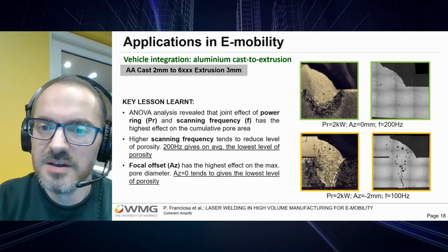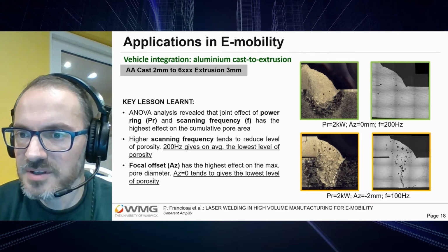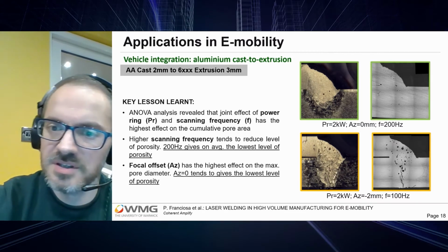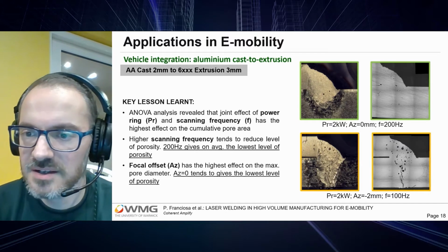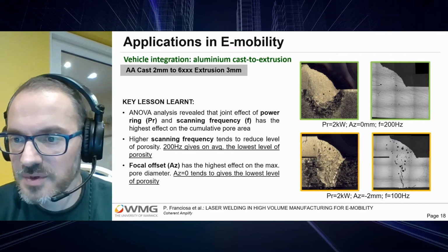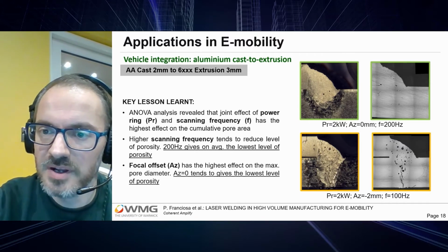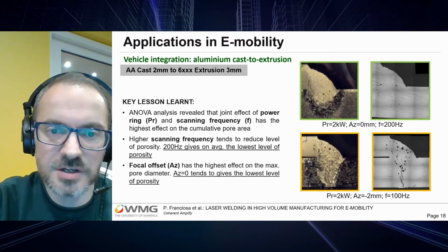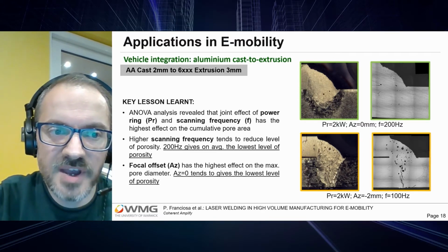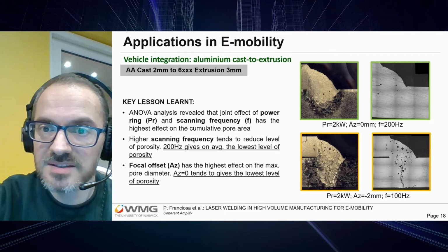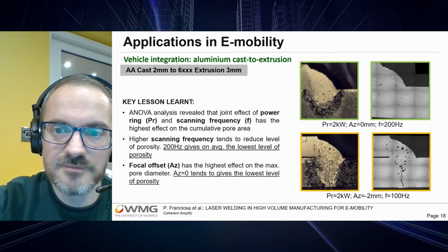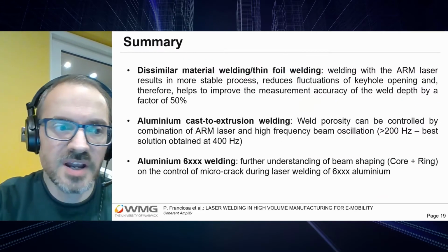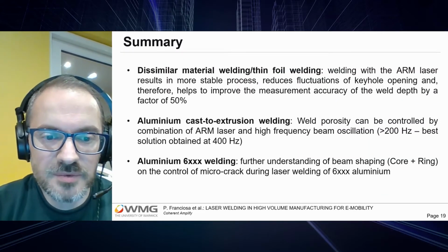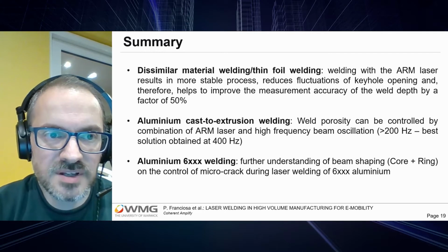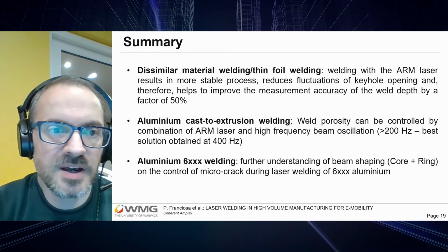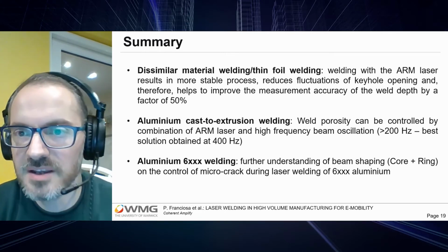So the top one is probably one of the most optimized, with the minimum level of porosity. The bottom one is the unoptimized one, where we have significant porosity within the weld. So really, the combination of scanning frequency and ring power has a beneficial effect on the weld quality overall. Now, if I can conclude where we stand at this moment, I have shown three applications. The first one was a thin foil dissimilar material.